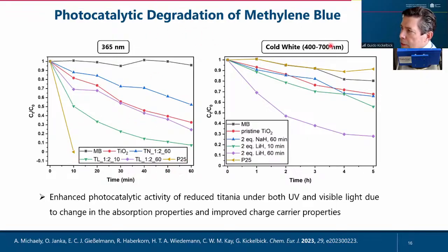This is a standard test with methylene blue under two different wavelengths. One is in the UV region and one is in the cold white region. So 400 to 700 nanometer and 365 nanometer. The standard reference is P25. This is an Anatase reference. And for the decomposition, what you see here is that the decomposition of methylene blue in the P25 case goes on very fast.